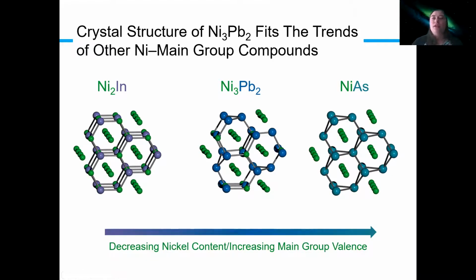the main group layers. And what we can see from this is that there's a decrease in the nickel content with the increasing main group valence. So it fits right into the trend that we saw at the beginning of this talk. But the really exciting thing about this is that the structure is metastable at ambient conditions, meaning that we can extend our intuition from ambient pressure up to our high pressure